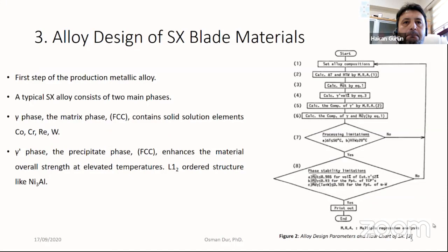Alloy design is the first step for development of a metallic alloy. You can see an example of alloy design in the figure. Single crystal alloys have different phases. However, the most important 2 phases are the gamma and gamma prime phases. Gamma phase, the matrix phase. This phase can be observed as a face-centered cubic form and contains solid solution elements: cobalt, chromium, rhenium, and tungsten.